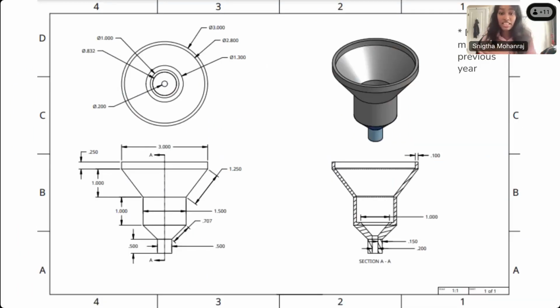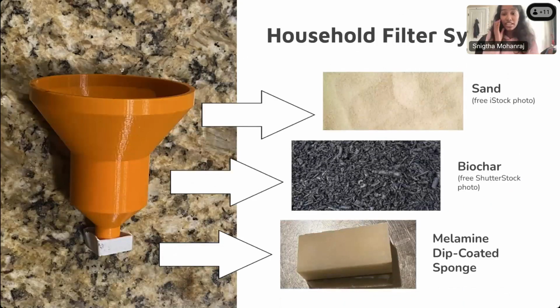And then this is a design that I made in previous years for a household filtration system. So I made this in the past, but I do think it's very helpful, and that's why I'm trying to build on it, because the compartment system means that I can use sand in the top compartment to remove larger contaminants like plastic and glass. And then my past research has showed that biochar is very effective for removing other contaminants like pharmaceuticals and pesticides. And the melamine dip-coated sponge using the sodium alginate, clay, and ionic liquid would be found at the bottom.